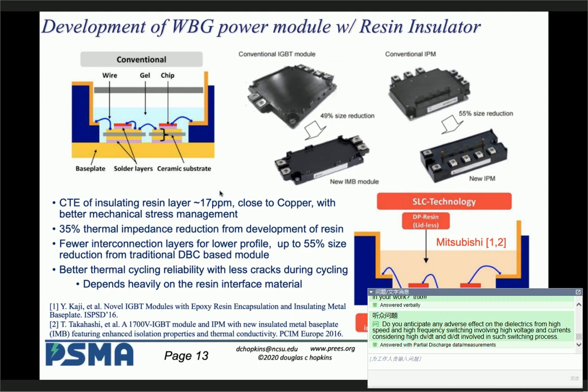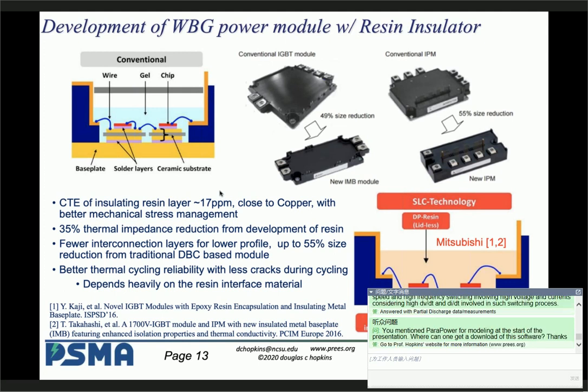I mentioned before how you have thermal spreading depending on how thick your copper is, et cetera. When it gets to the back of the module, if you use a constant plate temperature across the whole back, you're not including any spreading effects. Whereas if you put a heat convection coefficient H on the backside, now you're getting much more of a true understanding of where the heat is going to be liberated on the backside of your module and how that reflects to your total thermal resistance. It's one thing to set the thermal resistance with a backside fixed temperature, but it's something else to actually say, okay, in the application, what can I expect out of this? And without that H factor, which EEs typically don't include, you're not getting a really true understanding.